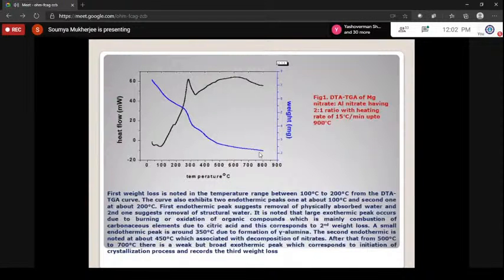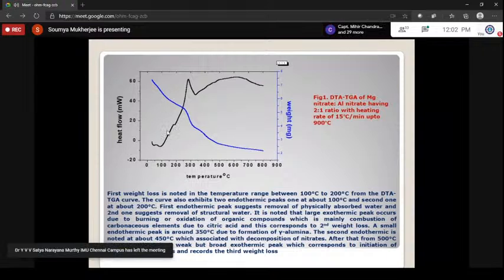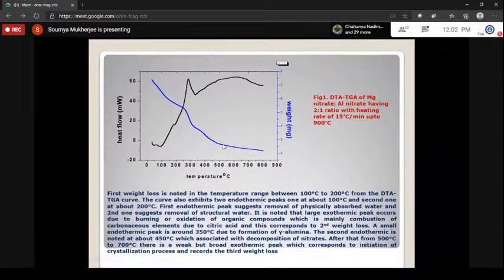Now, the results and discussion. The first part is the thermal analysis. From the thermal analysis, we are indicating the crystallization zone, that is the heat treatment zone. The weight losses are indicated up to 300 and above 500, but the weight loss above 500 is quite flat in nature, which indicates our heat treatment zone. The initial weight losses are mainly due to hygroscopic moisture, the crystal structures, the nitrate salts, and formation of gamma alumina, which is actually a low temperature compound. At higher temperature, this transforms to spinel. So that's why we are getting flat zones.